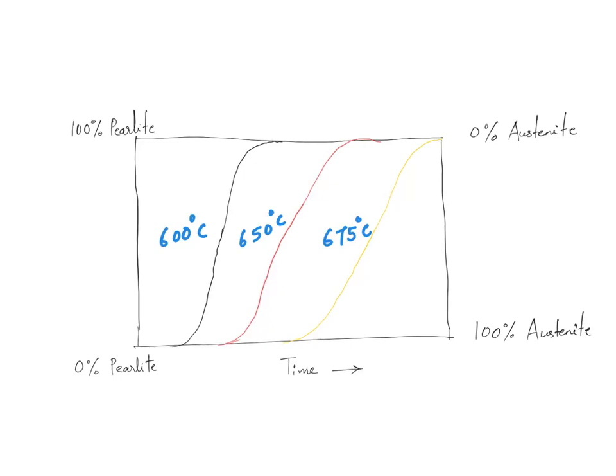The inferences from this plot: the amount of subcooling from the eutectoid temperature of 727°C clearly influences both the time for the reaction to begin and the time for complete transformation. When subcooling is high, the reaction starts faster and the rate of transformation is more rapid. So the higher the amount of subcooling from the eutectoid temperature, the higher the rate of transformation.